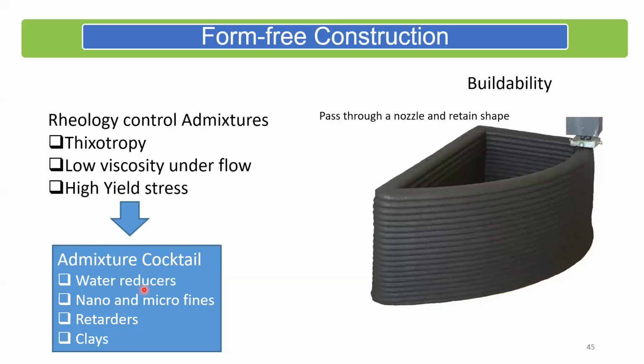We use a lot of nano and microfines now, because with this thixotropy, we are realizing that in order to be able to make these cementitious materials thixotropic, not necessarily set, but thixotropic, that means the internal structure inside the material starts building up. That I can achieve using these nanomaterials or microfines. And we are realizing now we can use clays, attapulgite and bentonite. These are the clays that we are using to produce this property of thixotropy. So in cementitious systems now, we're starting to add a little bit of clay to be able to get this, so that we can start building on layers to assemble the whole structure.